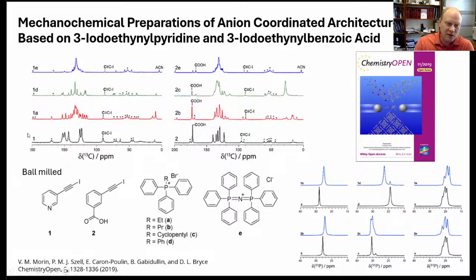And on the left, for example, for donor 1, we have a spectrum here. And you can see the 3 stacked above here, for example, cocrystals 1A, 1D, 1E. We get clear differences in the spectra, attributable to obviously some change in the crystal packing, in this case, the formation of a cocrystal. We can zoom in on particular peaks, for example, the alkynyl carbon, and monitor very clear changes in that chemical shift. So a way to very clearly see product formation, and also a way to assess purity, because we have no overlap with the starting material.